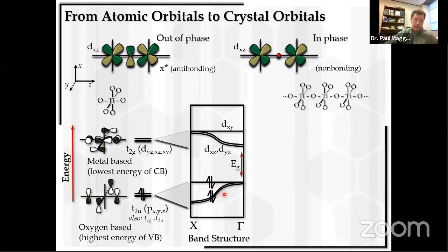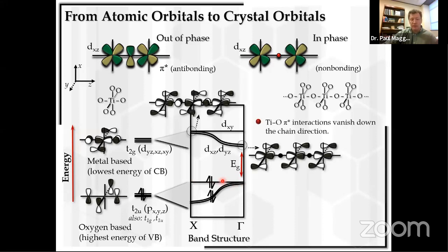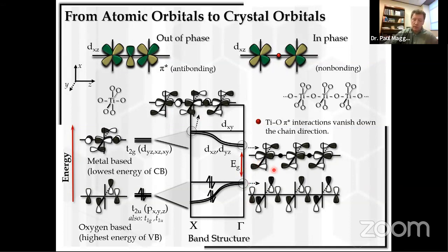And conversely, the band structure down in the filled levels for the oxygen orbitals, the highest energy levels remain the non-bonding energy levels. Okay, and so here, for example, this would be the crystal orbital at the X point in K space, as I described. This would be the crystal orbital at the gamma point in K space, as I described. You see now that there are nodes, and the difference in energy between this crystal orbital and this crystal orbital is the extent of the interaction between the p orbital here and the d orbital here.